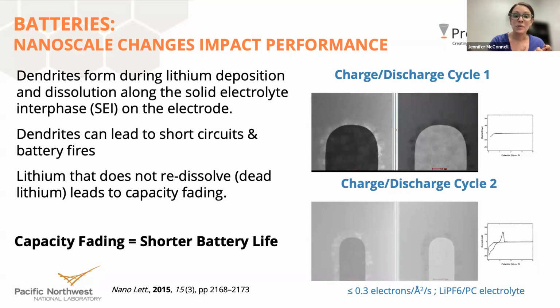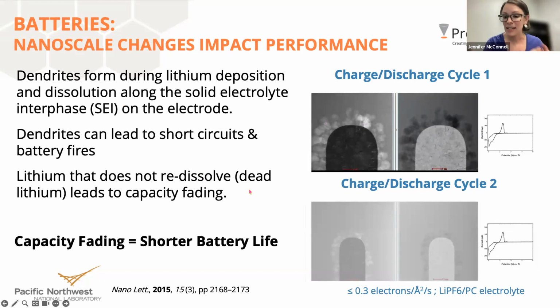And then as we sweep back into the positive direction, you're going to see a partial redissolution of the lithium back into the electrolyte. And the problem is what didn't dissolve, right? This is dead lithium. And as you continue charge and discharge cycles, so here's a second one, same everything, we just zoomed out a little bit. You're going to see that deposition and that partial redissolution again, but of course you've got more dead lithium. And with each cycle, you get more and more.